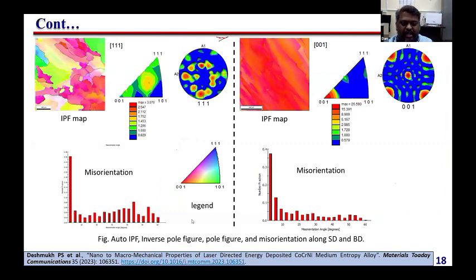When we looked at the EBSD, we understood that in the scanning direction, in most cases the grains are elongated, a very coarse structure. But in the building direction, almost all the grains are columnar, grown epitaxially. Interestingly, the texture is also very different. In the building direction you can see the same color, and the same color means all the grains are oriented in a similar orientation.